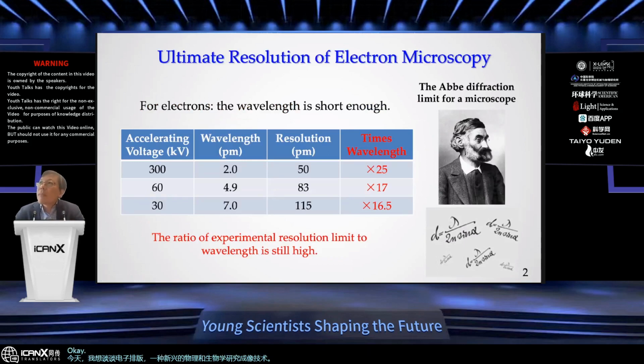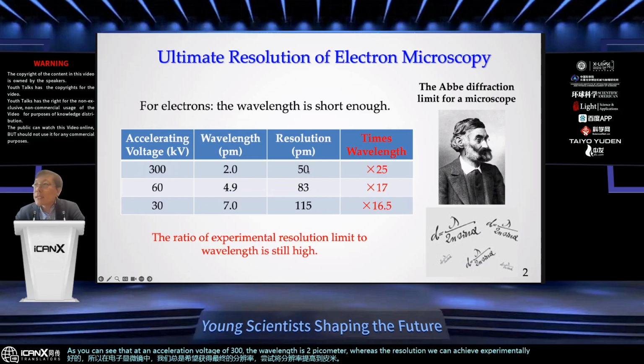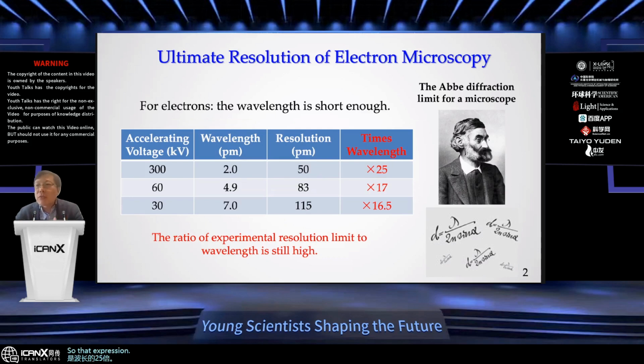In electron microscopy, we always would like to achieve ultimate resolution, trying to improve the resolution towards the picometer. As you can see, at an acceleration voltage of 300 kV, the wavelength is 2 picometers, whereas the resolution we can achieve experimentally is 50 picometers, which is 25 times the wavelength. So the ratio of experimental resolution limit to wavelength is still high, and we need to continue to improve the ultimate resolution down to the wavelength limit.